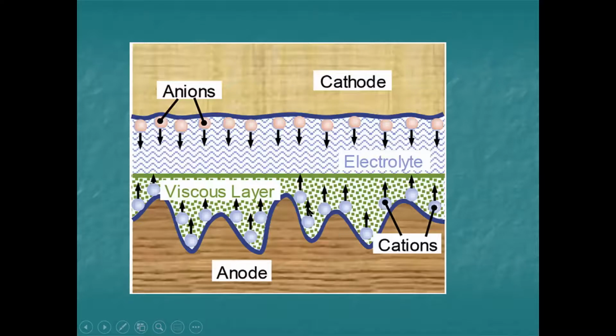They can't mix up. And that means the diffusion length is much less for the top of a peak than it is for the bottom of a peak. So since the process is diffusion controlled, when the diffusion thickness is small, like it is on the top of a peak, we're going to get much more activity here than we will at the bottom of the trough, where the diffusion length is much longer. And that's why we need the viscous layer, so that the mechanism is only by diffusion and not by convection.